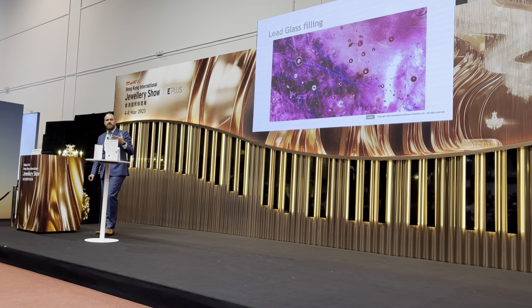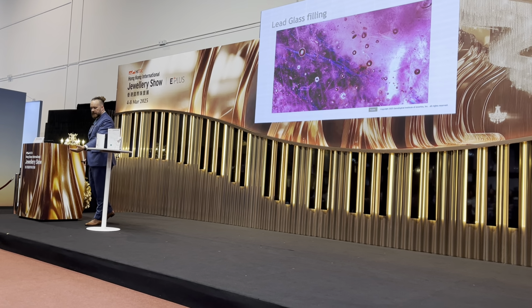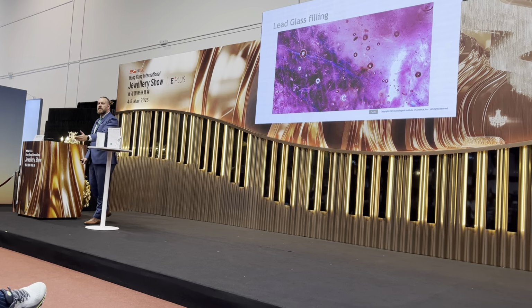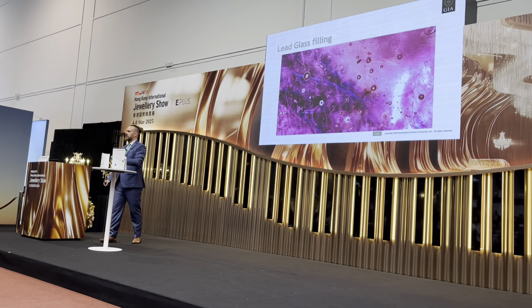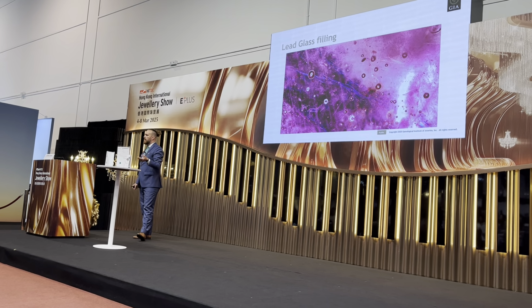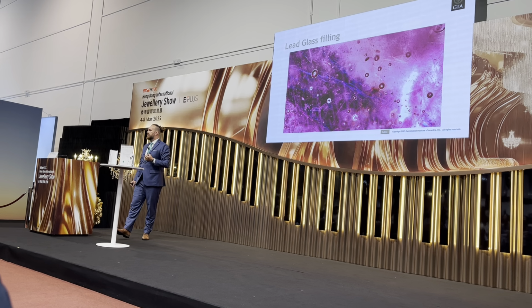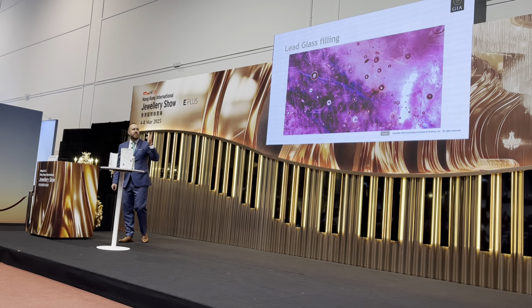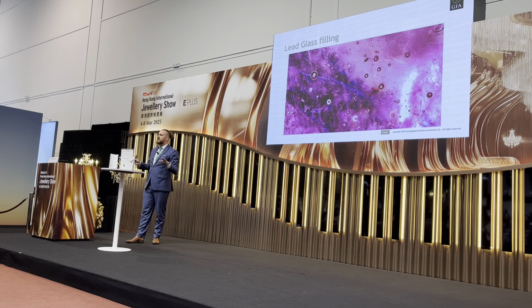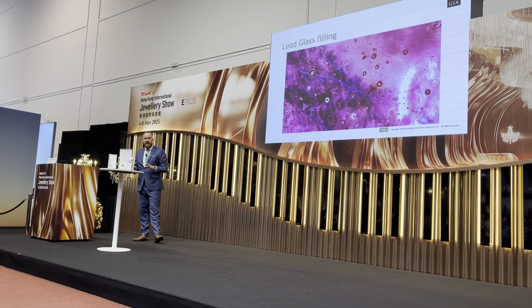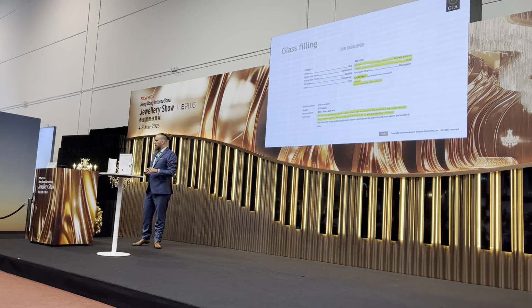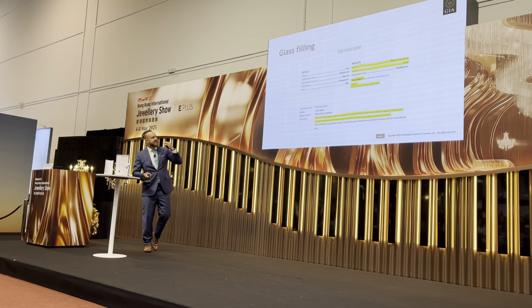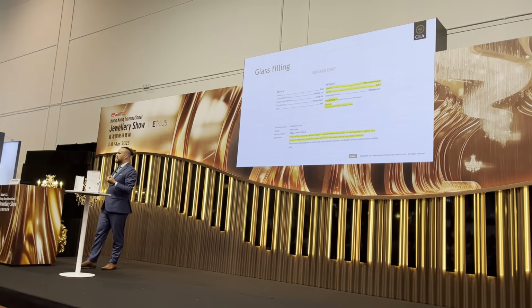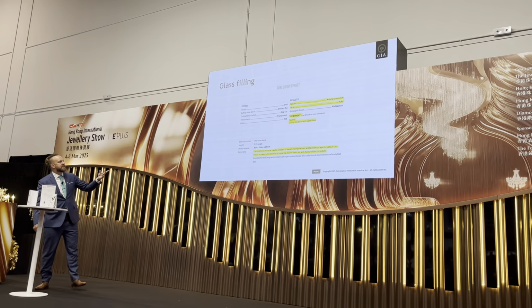Sometimes in a lead glass filled stone, even if you look at it like this, you sometimes see a very suspicious blue flash or a green flash in it. That is the lead glass filled fracture that you can see in there. But even with a loupe, this is probably the easiest treatment to detect. So when that gets put on a report, that is still a natural corundum, that is still heated because this process only happens at high temperature, but it will say that it is clarity enhanced with lead glass.